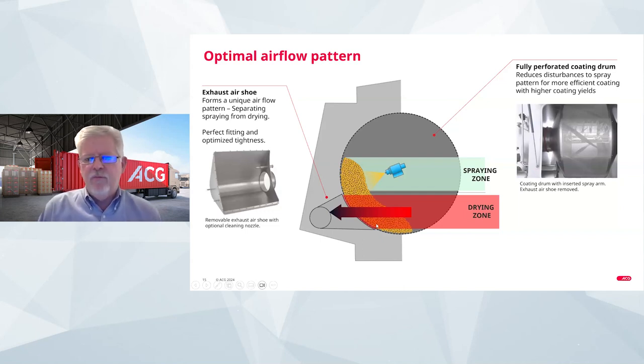Now, one of the aspects of modern coaters that most customers are looking for is a wide range of operation. And although we'll get into that aspect a little bit later, one of the other key aspects is this exhaust air shoe. And it's critical that the exhaust air shoe be sized such that the cross-sectional area and the air that's being drawn through the tablet bed itself does not provide any ability for the air to bypass the tablet bed. So if the tablet bed would be small enough that the exhaust air shoe would have an area of the drum that is not covered by tablets, you would see air bypassing the bed as shown in the graphs that Shantanu showed earlier. The current designs of units are designed so that this exhaust air shoe is sized so that at the minimum tablet load in a drum, there's no ability for the air to bypass the tablet bed.